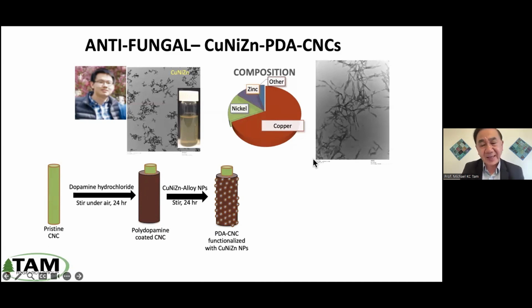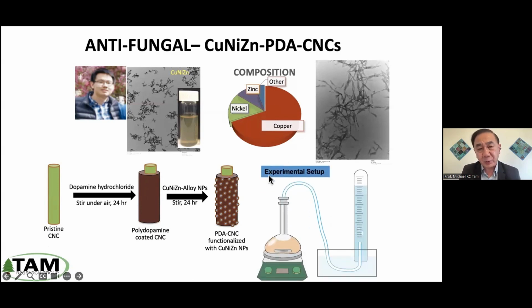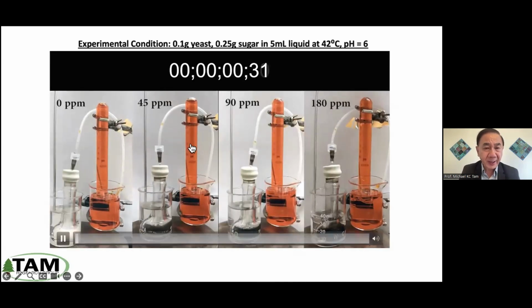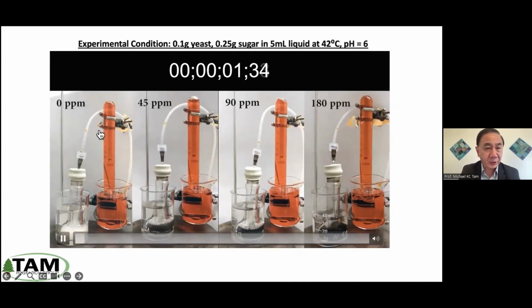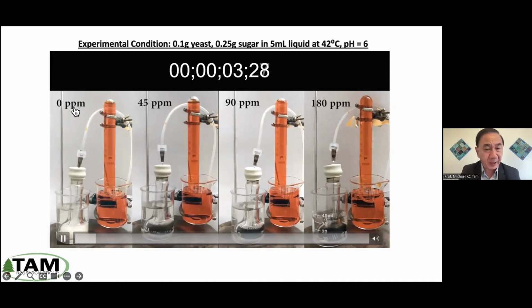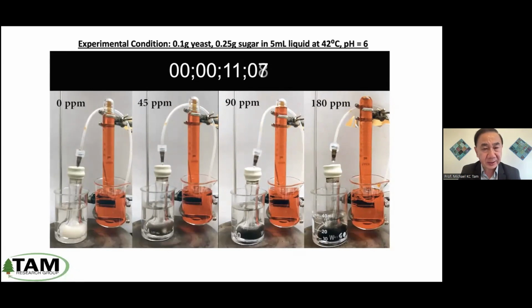So we have a very simple assay to try to evaluate their performance. What we do is that we culture yeast, baker's yeast, with sugar, and then we add different amounts of nanoparticle to this yeast system, and then measure the amount of CO2 release as an indicator of the impact of the material on the antifungal property. So here's the illustration. On the left is a control with 0% of this compound, and then from left to right, you have 45, 90, and 180. So we measure the CO2 release from the inverted U tube, and then from the volume of this CO2, we can then plot this relationship.